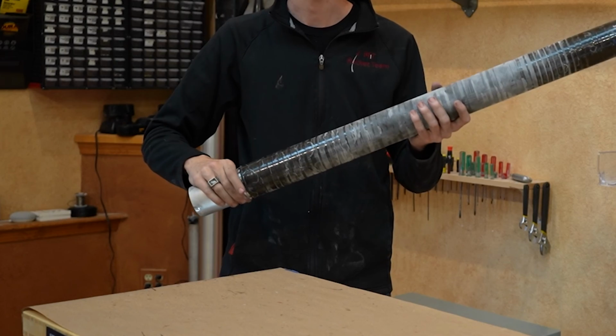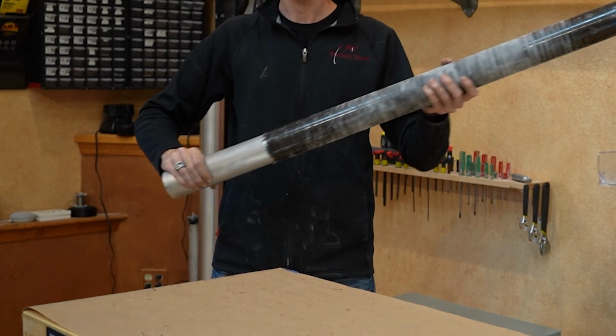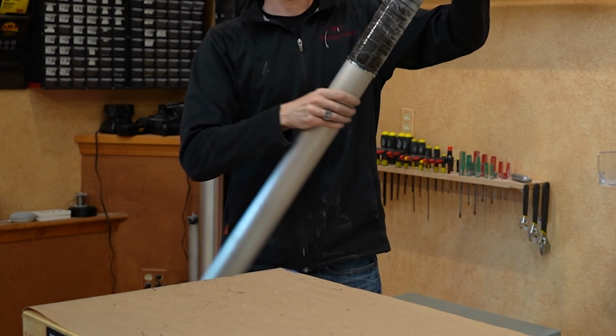Once the tube had cured, I removed the Teflon tape holding the mylar film onto the mandrel, and I was able to slide the mandrel out from inside of the tube. The mylar can be pulled out from inside of the tube, leaving a clean surface on the inside.